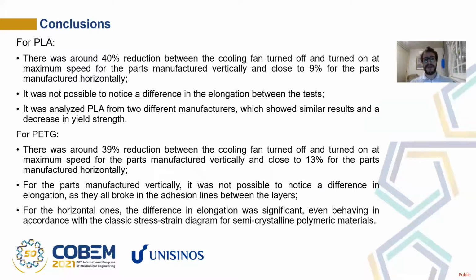The conclusions then are that there was a reduction of 40% between the cooling fan turned off and on at maximum for the parts manufactured vertically, and of around 9% for the parts manufactured horizontally. There was not really a difference between the elongations between the tests, and these both manufacturers behaved really similarly. As to PETG, there was a reduction of around 39% between the cooling fan turned off and on at maximum speed for the yield and rupture strain.